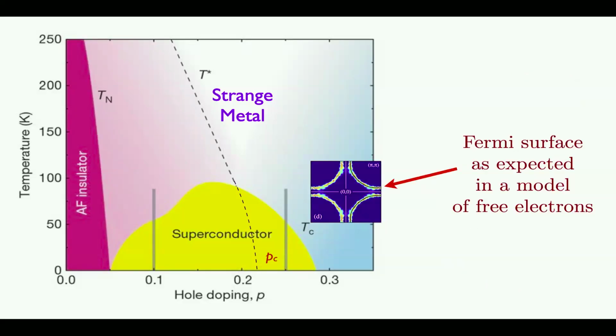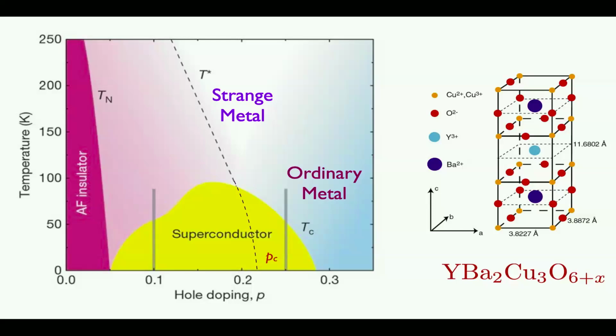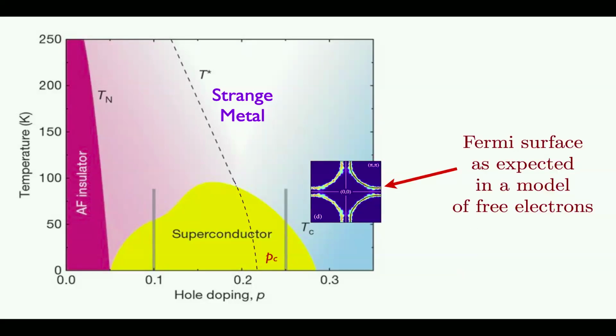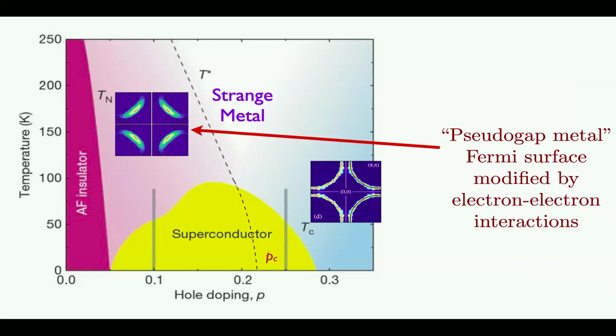All right, so I want to say something about the Fermi surface, which we can measure in photoemission experiments. So what we know is in the ordinary metal, the Fermi surface is exactly what you'd expect from Landau's Fermi liquid theory. You can just treat the electron as free, and this is the boundary between the empty and occupied states, just as would be the case for a model of free electrons. On the other hand, at low doping, you don't see that. You see some state that people call a pseudogap state. Pseudogap because there's no low energy excitation in this region. And what it is, well, I'm going to just sidestep that question given the short time available, but I'm happy to discuss that in much greater length with you later.